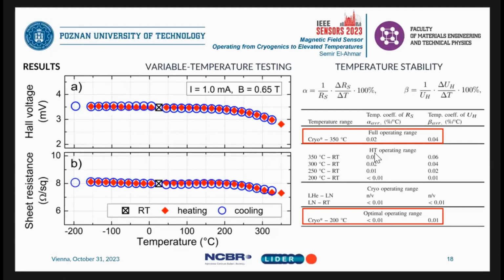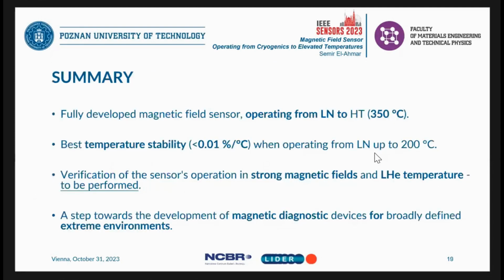To sum up, we developed a magnetic field sensor that can be operational from cryogenic temperature up to a high temperature of 350 Celsius degrees at least. We find the best temperature stability, shown by appropriate temperature coefficients, when the sensor is operating from liquid nitrogen up to 200 Celsius degrees.